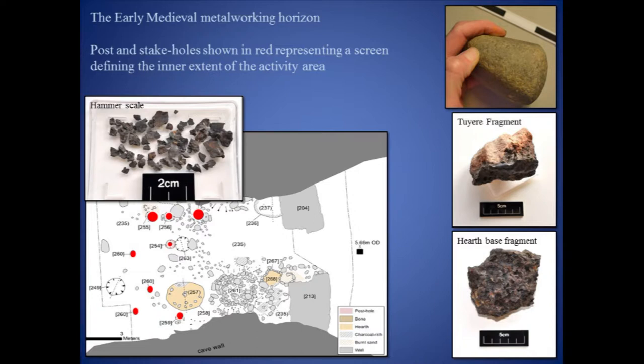The sandy floor layer forming the metalworking horizon produced slag deposits, plano-convex hearth-base fragments, and some vitrified residues, including one large clay fragment forming part of the tuyère — the hole through which the bellows injected air into the furnace. Processing of the sediment samples taken across the metalworking horizon produced hammer scale, and preliminary analysis by Gemma Cruickshanks at National Museums Scotland suggests that possible bloom refining and smithing was taking place in the cave.